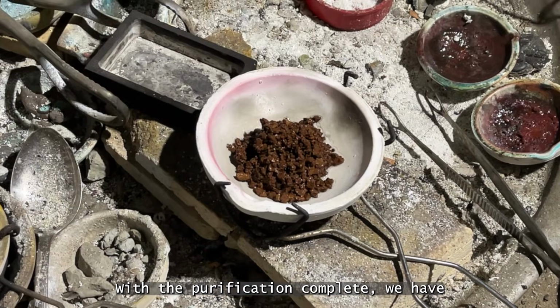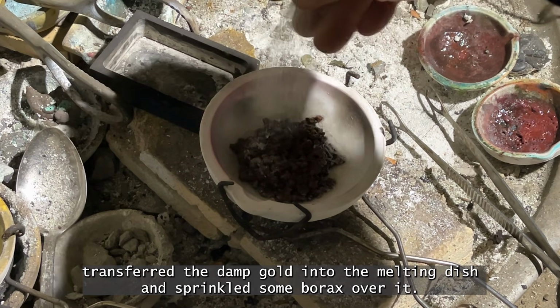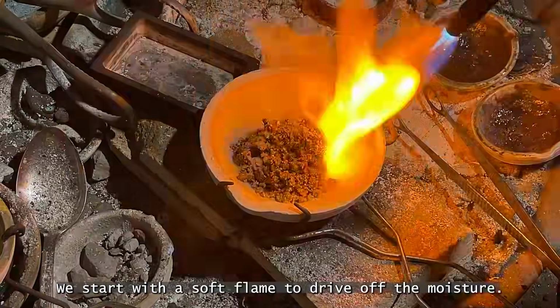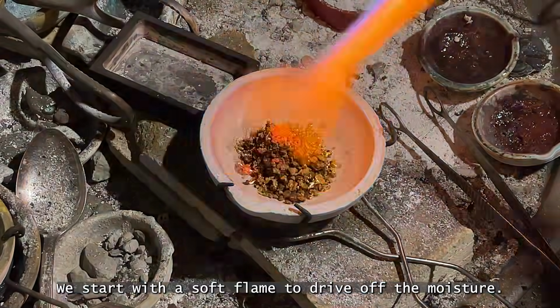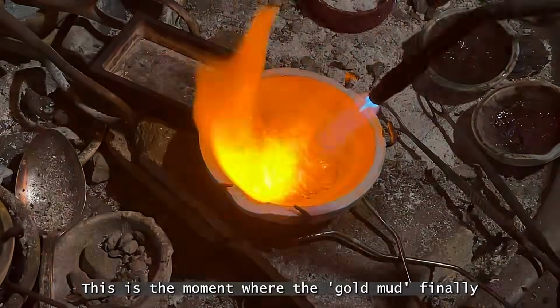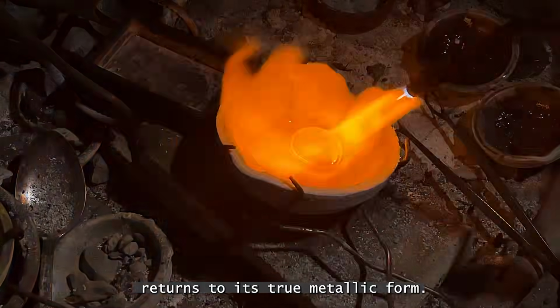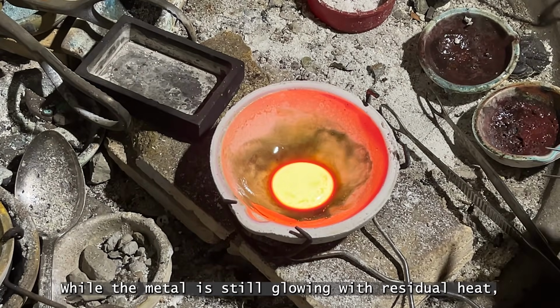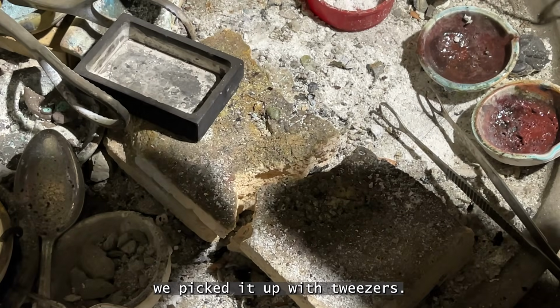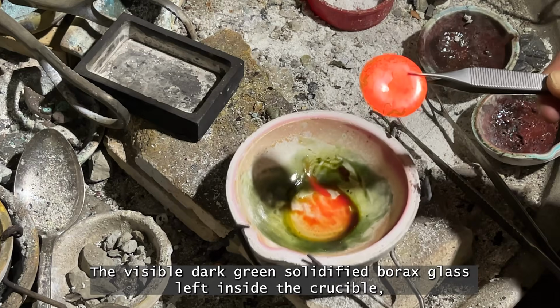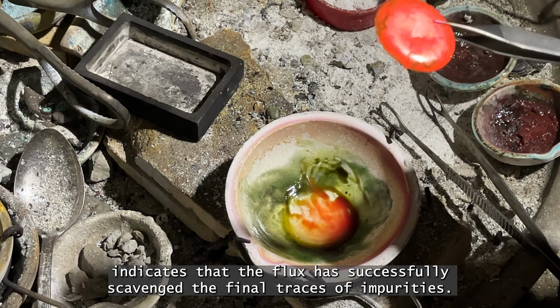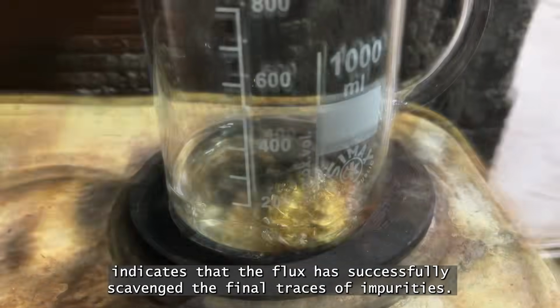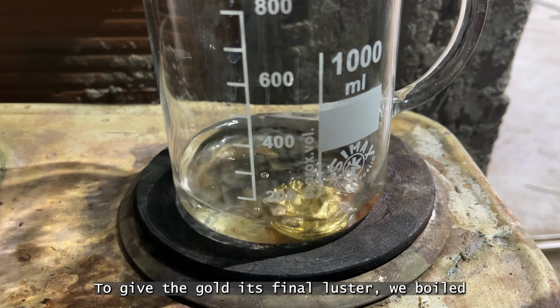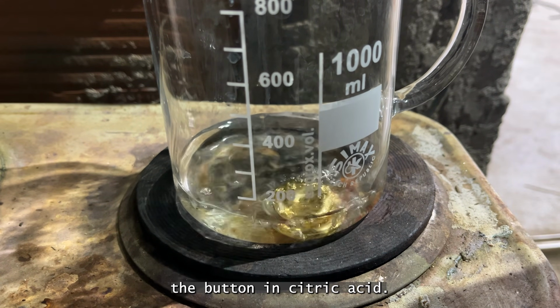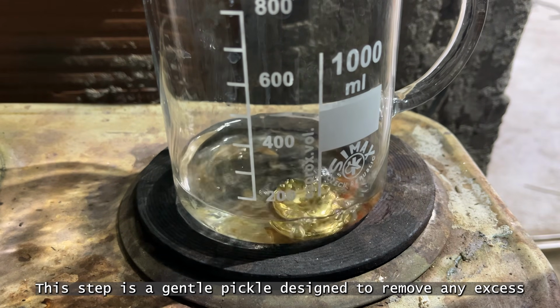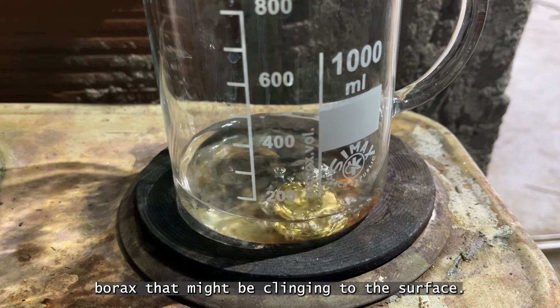With the purification complete, we have transferred the damp gold into the melting dish and sprinkled some borax over it. We start with a soft flame to drive off the moisture. This is the moment where the gold mud finally returns to its true metallic form. While the metal is still glowing with residual heat, we picked it up with tweezers. The visible dark green solidified borax glass left inside the crucible indicates that the flux has successfully scavenged the final traces of impurities. To give the gold its final luster, we boiled the button in citric acid. This step is a gentle pickle designed to remove any excess borax that might be clinging to the surface.